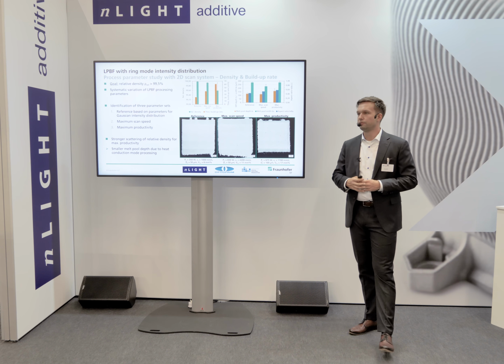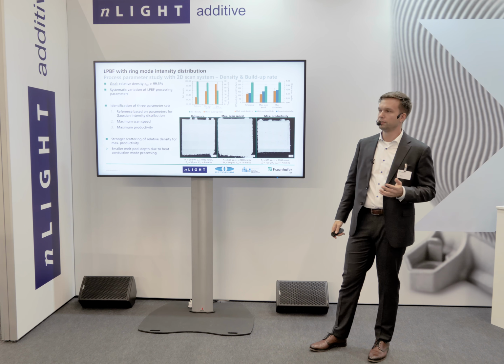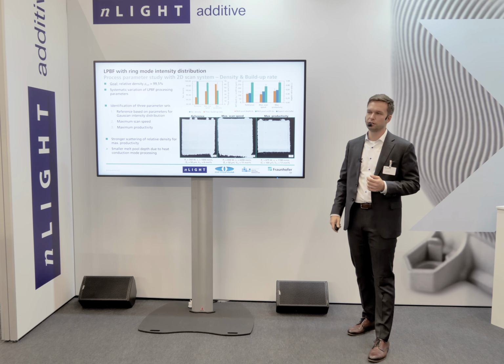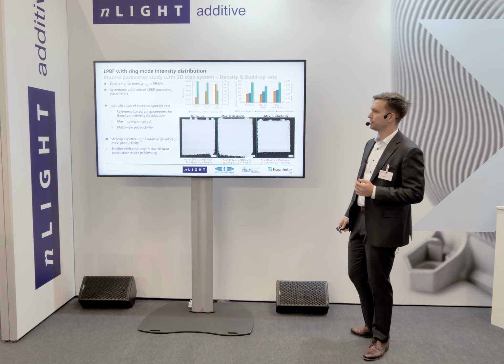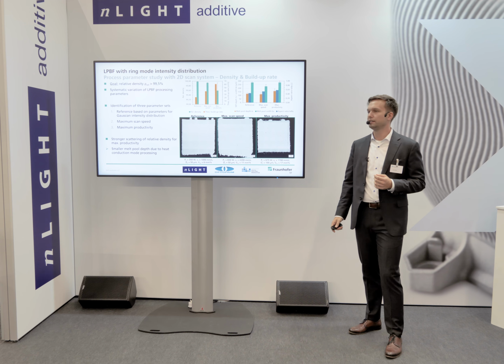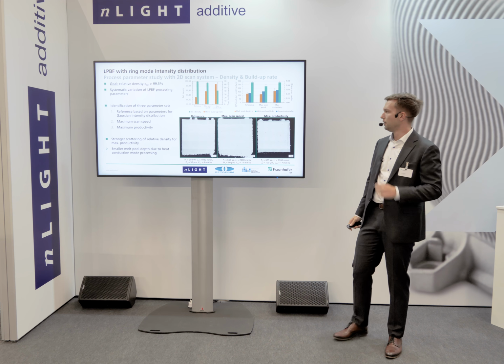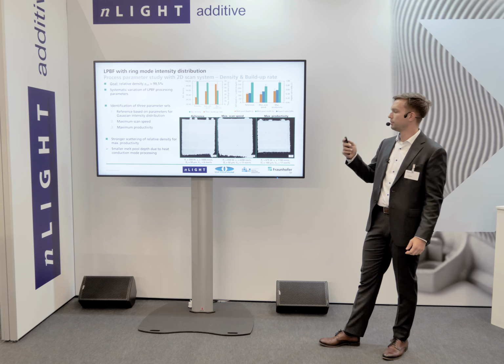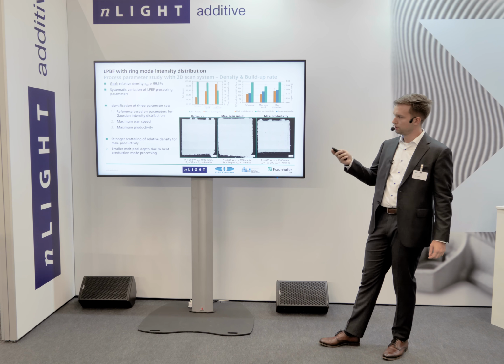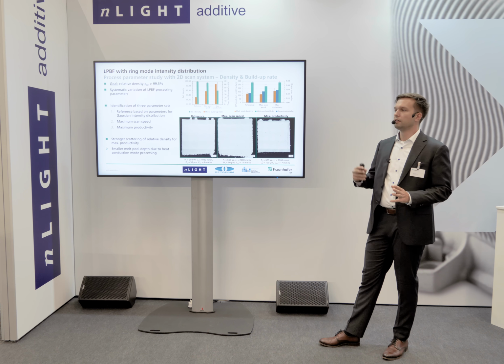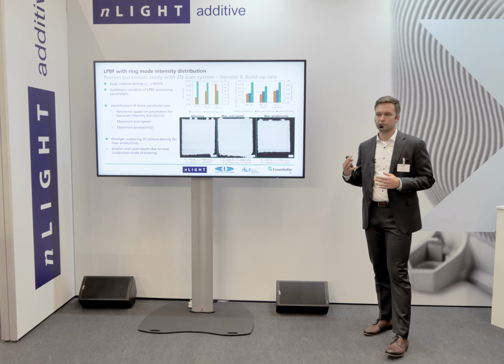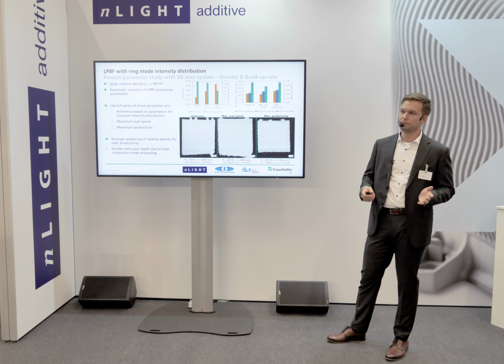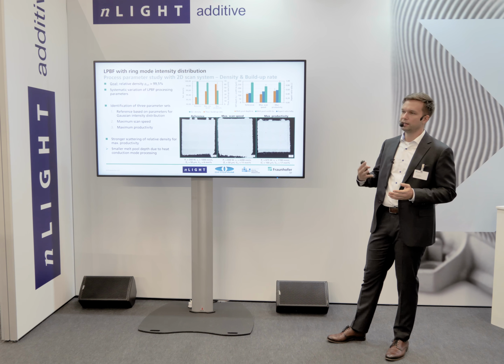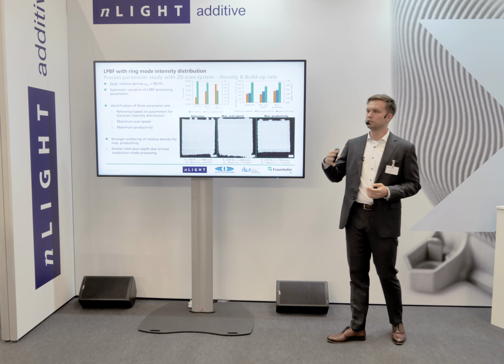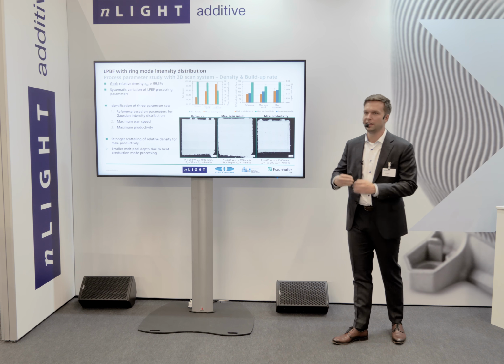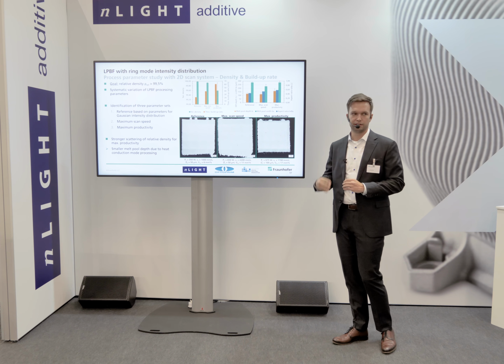Additionally, we tried to do some first test cubes with the prototype to see if it also works in the process. We varied all the processing parameters and identified suitable process parameter combinations that yield density above 99.5% while maximizing the productivity. And we found 3 parameter sets that we compared, which is on the one hand side reference, so parameters very close to the ones you use for single mode Gaussian laser beams. Then max scan speed, which means maximizing scan speed while keeping a layer thickness of 50 microns. And then we also tried to maximize productivity, so also scaling layer thickness to even get a higher productivity.